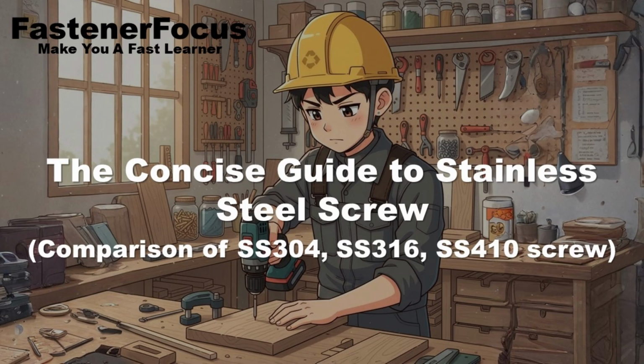performance. Finally, the star of the show for corrosion resistance in aggressive environments, molybdenum or Mo. Molybdenum is the crucial ingredient that separates the good 304 from the great, which is 316. Grades 304 and 410 have essentially zero molybdenum. Grade 316, however, includes a substantial 2 to 3% molybdenum. This is the marine factor. This molybdenum addition dramatically increases 316's resistance to the two most insidious types of localized corrosion, pitting corrosion and crevice corrosion, particularly when chlorides are present.